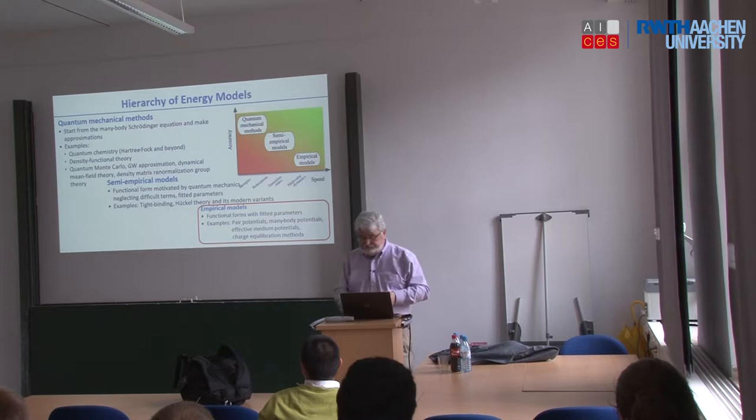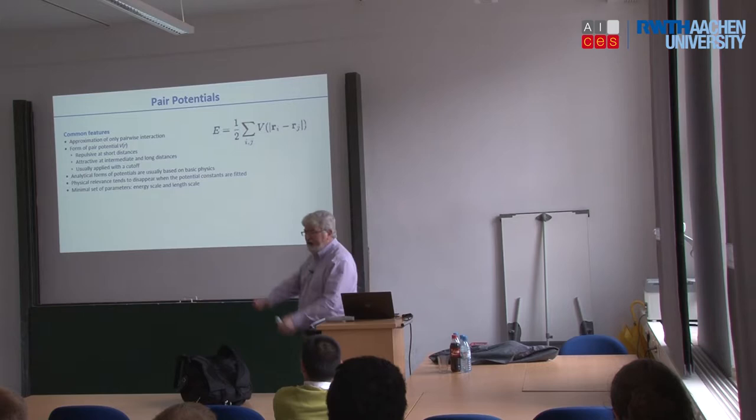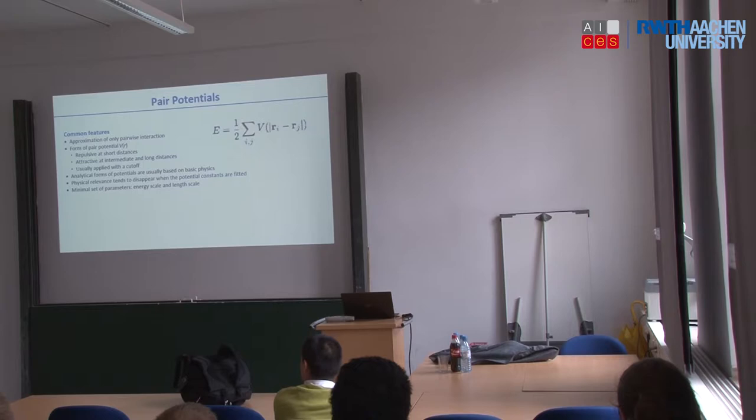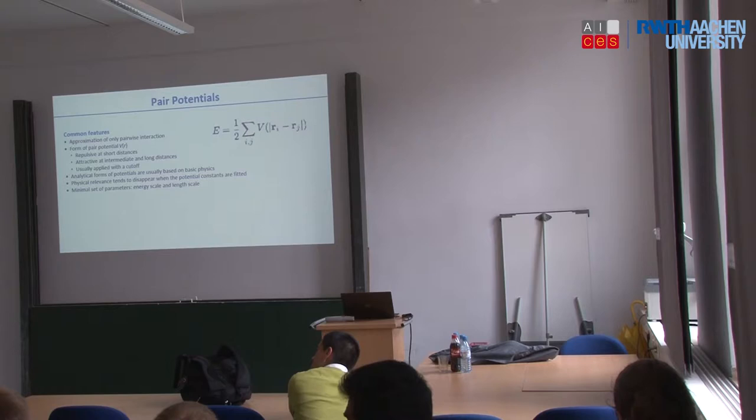Okay. So pair potentials. The idea of a pair potential is that the energy of an atom, my energy, just depends on my interaction with my neighbors. So how close you are to me, you are to me, you are to me. And I probably don't care about you in the back corner. You're far enough away, I can probably ignore your interaction with me. So we just calculate these individual interactions and add up what those forces are. And that's the force on me. Likewise, the force on Doctor Who includes an equal and opposite contribution from me. But now he may care about the people in the back row because he's a little bit closer to them. They may interact with him as well.